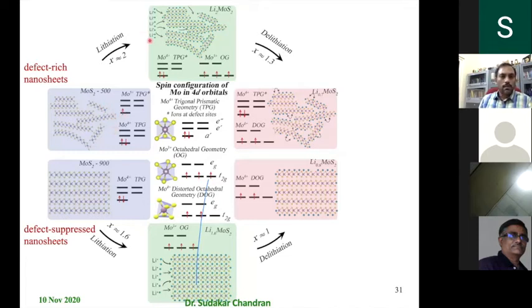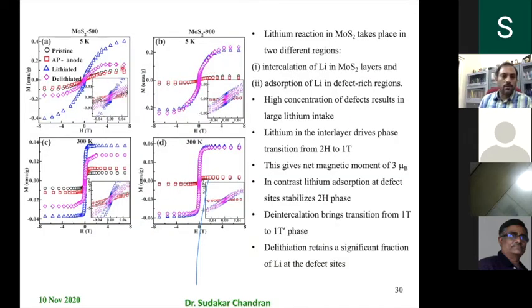Now, when you put lithium into this, 2 lithium is taken, and these lithium go in between the layers, and also go onto the defect sites, and then get trapped or adsorbed. So you have moly 4+ going to moly 3+, and also these moly 5+ go to moly 4+. If the trigonal prismatic configuration is, I think mostly it is, at a defect site it doesn't go to the octahedral geometry, and in trigonal prismatic geometry, you have a diamagnetic state. So the magnetic property that was coming from the defects disappears, whereas the diamagnetic state of moly 4+ becomes magnetic now. Of course, this is a large concentration. Therefore, you see a big jump in the magnetic property here.